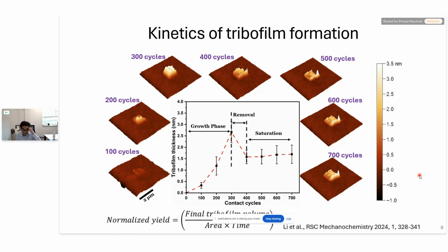Based on these measurements, we can then calculate the yield of the tribofilm, which here we call the normalized yield of tribofilm, which is the overall volume of tribofilm generated by the end of the experiment, divided by the area over which the tribofilm was generated, divided by the time it took to generate the amount of tribofilm. So essentially, once saturation was reached, we were able to calculate the normalized yield of the film.